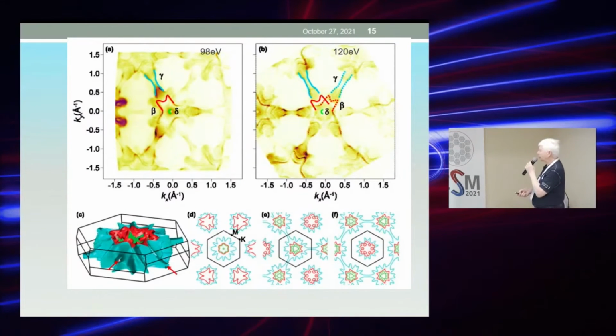The ARPES measured band structure is illustrated here. It shows different bands which have proper symmetry at different values of the momentum. They can be identified with different orbitals. So the result is very nicely consistent with theoretical calculations, and the total Fermi surface looks like this.